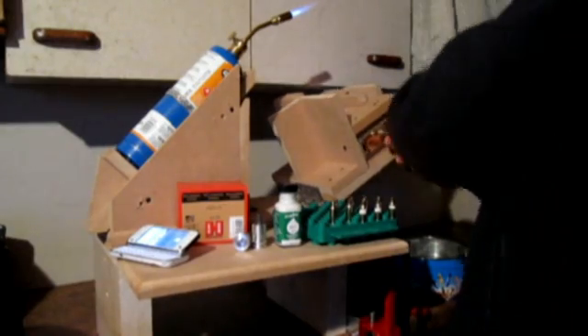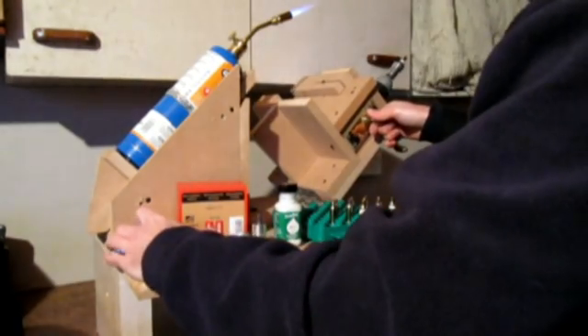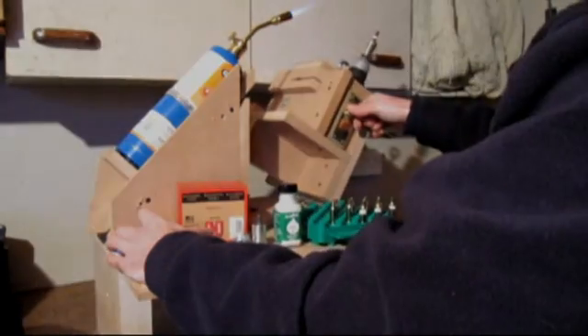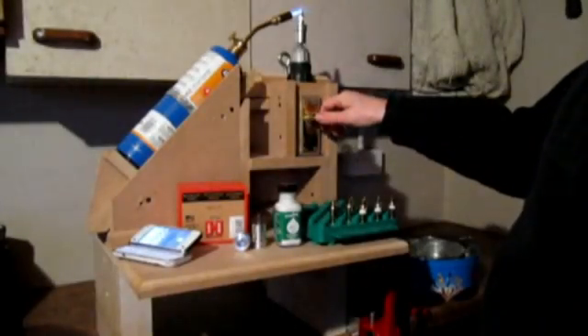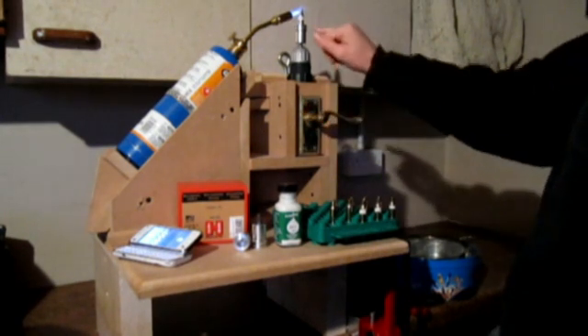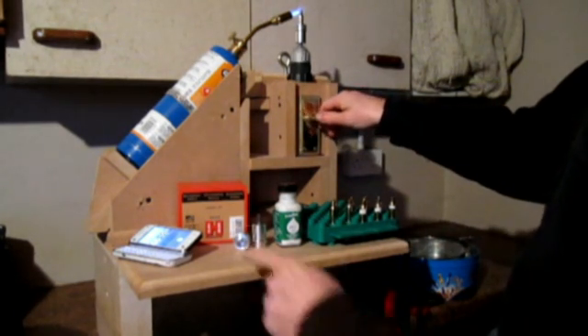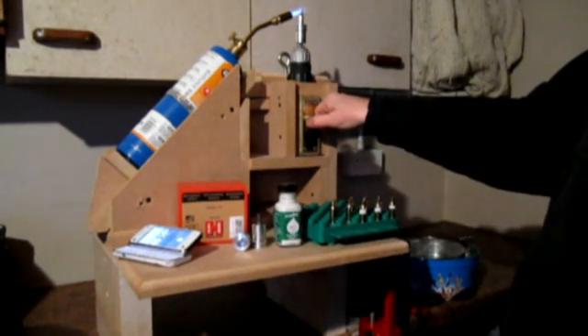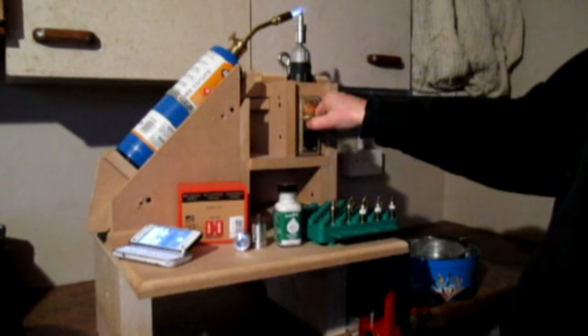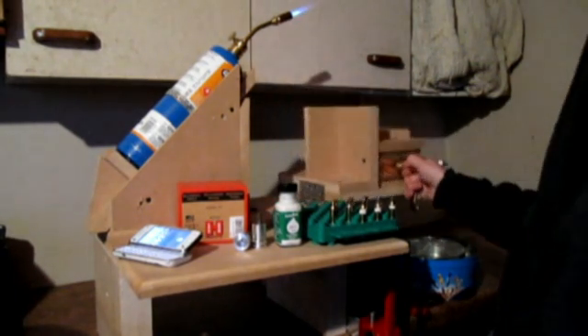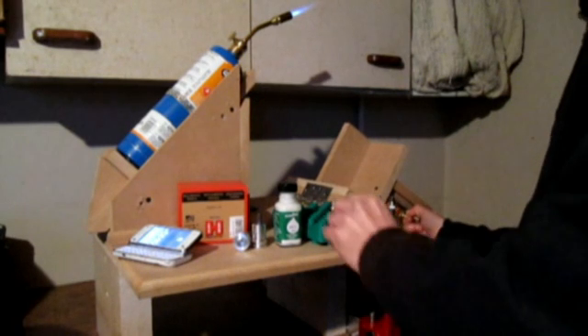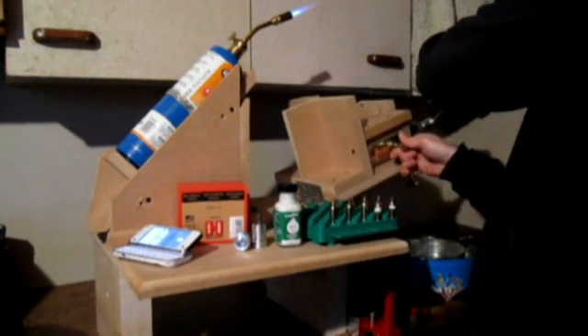Replace the second cartridge. Just want to start my timer as I bring it into the flame. Always watching the case, checking that the indicating liquid melts off. It will come from white to invisible. Just watching the clock. We're up at 13, 14, 15, 16, 17, 18, 19, 20. And tip. You hear that scent with the water cooling it down.